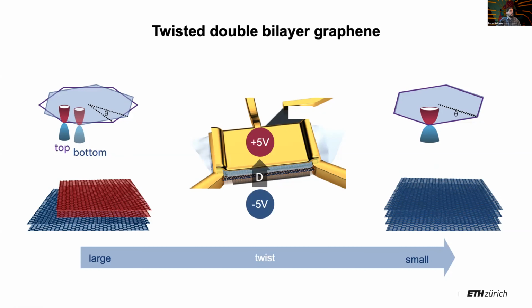And we interpret this now as only part of the wave function being gapped, while the other remains conductive. So you see you have these 4 bands. 2 of them are gapped, but 2 are not. So that's why the resistance just reaches a certain value, but not the same maximum value it has at 0 density. See also that the peak at 0 density stays in size.